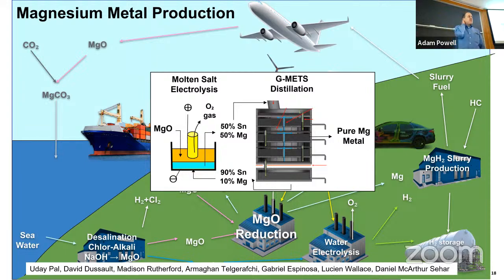What if we could do vapor compression distillation of magnesium? Well, what we could do then is use what's called a reactive metal cathode. Start with something like tin, and that enables us to do molten salt electrolysis in the same way that aluminum is made today. And it enables this because once we've reduced a bunch of magnesium oxide to metal, we basically take 90-10 tin-magnesium, increase the magnesium content, and produce oxygen gas, and then put it into this distiller and get out pure magnesium metal, and then tin with a little bit of magnesium left in it. So we get the pure magnesium metal out of that.